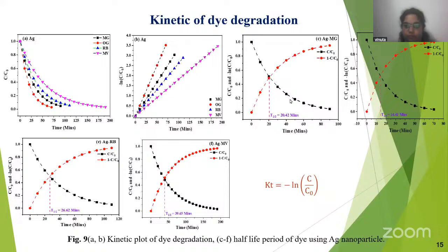Here, T half of MG green is like 20 minutes, and OG dye is also nearly 20, and rhodamine B is like 26.62, and MV dye is 40 minutes. So here we have used a rate constant with the help of Kt is equal to minus ln C by C naught. Here C and C naught are the concentrations. Rate constant K validated the strong catalytic activity of the silver nanoparticles. The excellent performance of the photocatalytic degradation highlights the effectiveness of silver nanoparticles in dye decoloration.